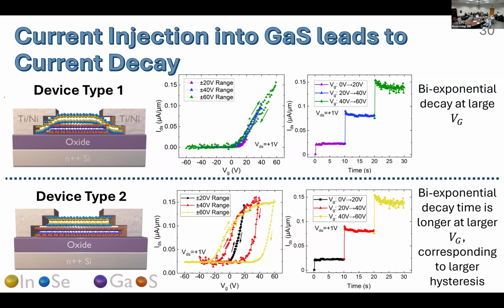And if you do it at a different rate, would you see a different hysteresis? Yes, yes. And that is because the relaxation times of these traps is different. So depending on the rate, the response of these traps will affect the hysteresis. If you scan at a rate much higher than these traps, then you might bypass it all and not see any hysteresis. If you go too slow, you might see them more obviously. Sorry, the width of the hysteresis will increase, and the current density will decrease.